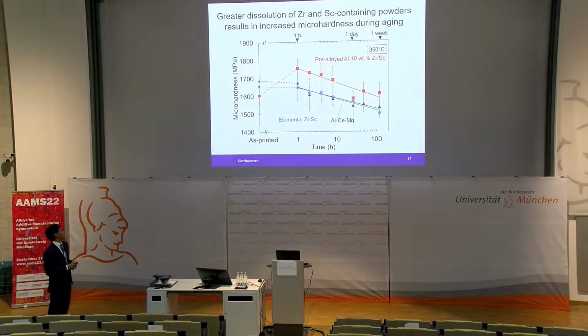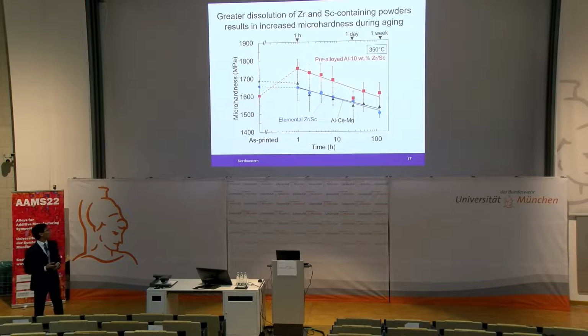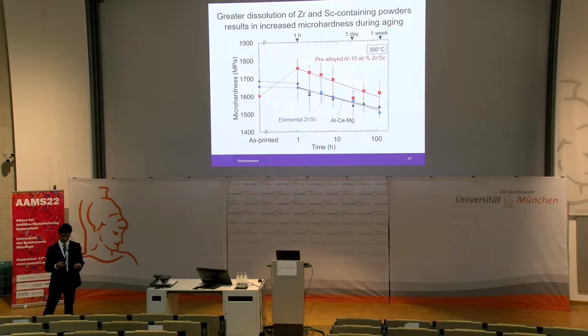Lastly, I'll talk about the effects on microhardness during aging. And when we take a look at the sample produced with elemental powders, we see no effect when we compare this to the base alloy without any sort of scandium or zirconium, owing to the fact that very little was dissolved during the melting process. Now, when we replace it with these pre-alloyed powders, we can measure a hardness increase during aging due to the fact that we have more zirconium dissolved, able to form more secondary L12 nanoprecipitates, providing an increase in hardness.